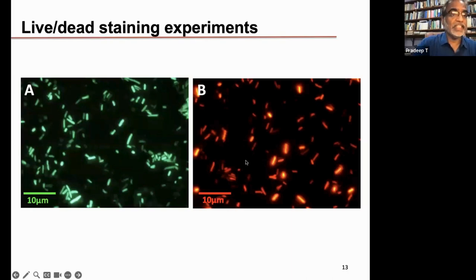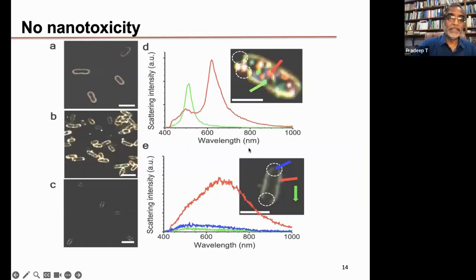And this is a staining experiment that biologists do to study whether material is effective or bacteria are dead or not. Well, when nanoparticles are used, even in the beginning of 2000, we were thinking that if it were to be used in water, nanoparticles should not be leached into water. That can cause nanotoxicity. So we deliberately put nanoparticles in water, and these are E. coli bacteria. They pick up nanoparticles, and that is what is seen by microscopy as well as spectroscopy.